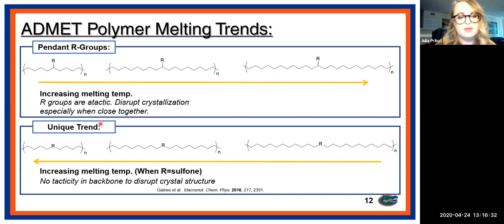A unique trend that we've discovered pretty recently is that in some instances, when the R group is a sulfone, for example, or incorporated into the chain backbone, it actually increases the melting temperature as you put the R groups closer together. And this is because there's no tacticity in the backbone to disrupt the crystal structure. I just want to point this out because it's going to come into play a little bit later in the presentation when I talk about secondary structure of precision polymers.